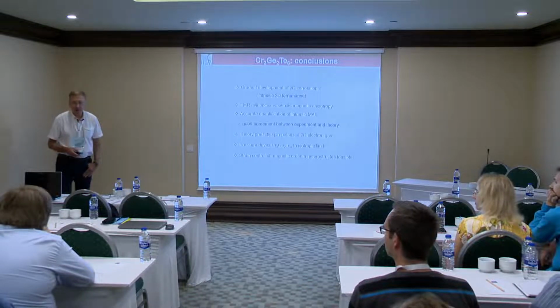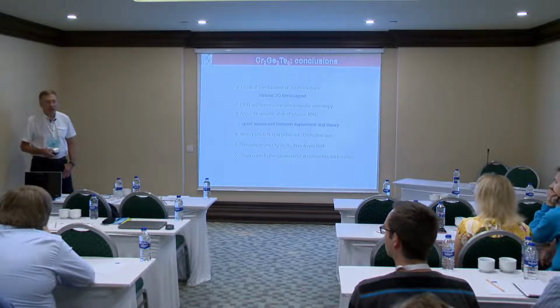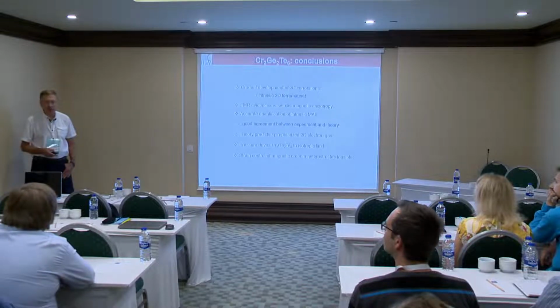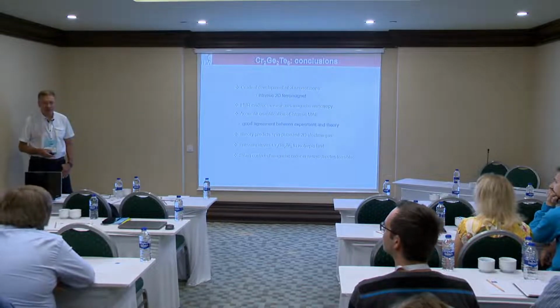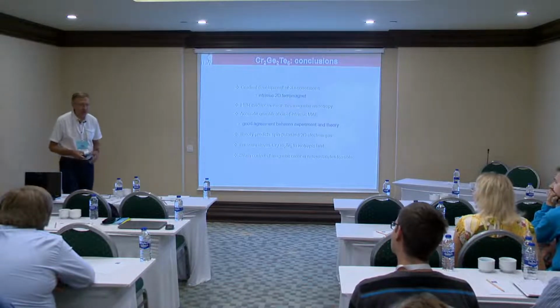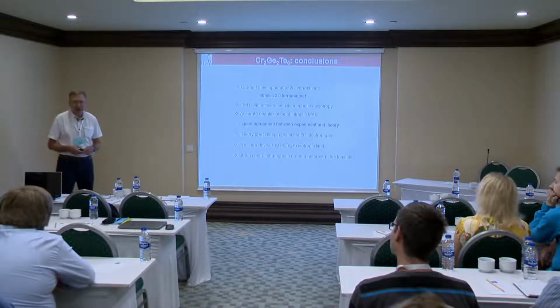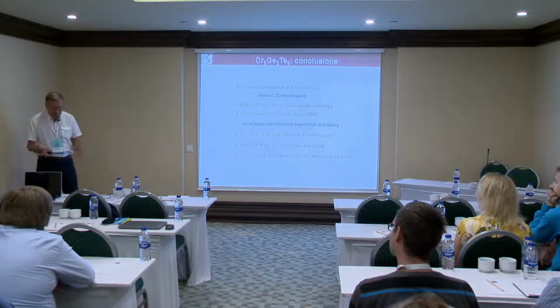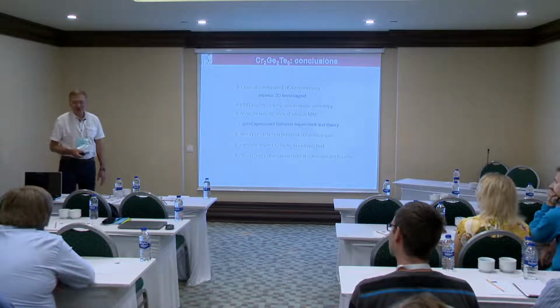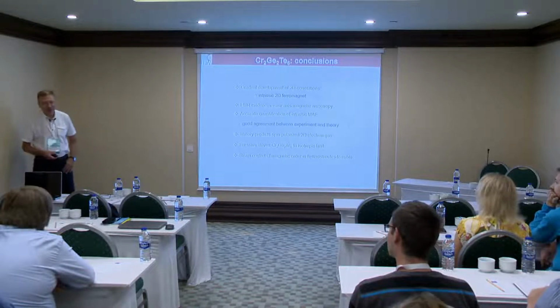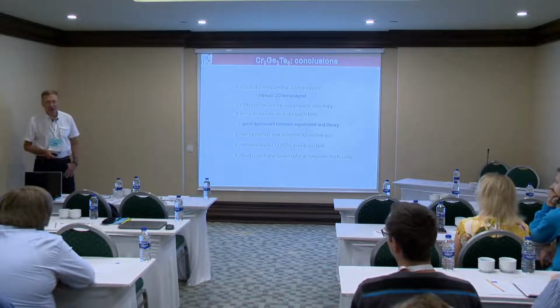Is it possible to measure flakes with your technique? Not in this pressure experiment, unfortunately, because the pressure cell reduces the sensitivity by orders of magnitude. You have a tiny sample in a very big pressure cell, which you have to expose to the radiation. So the density of the microwave radiation is really very small at the sample.